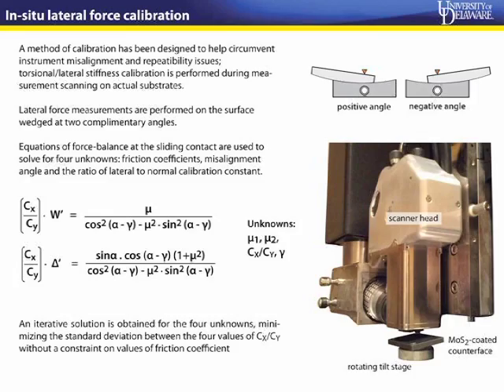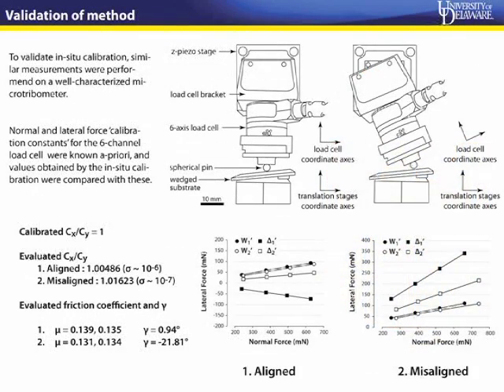Now that we have proposed this method, we want to see if it's actually valid. The validation was performed using a well-characterized microtribometer that we have in the lab. This is a schematic of the microtribometer where you have the vertical piezo stage back here, which moves vertically, and then the horizontal stage right here, which is also piezoelectric. You have a well-characterized 6-axis load cell, where the calibration is predetermined by the manufacturer, and CxCy is stated to be 1.